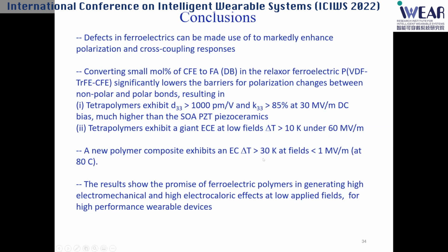We also showed that even new polymer composites, at very low electric field, can generate very large temperature swing. This result shows the promise of ferroelectric polymers in generating high electromechanical and high electrocaloric effect at low fields, which could lead to high performance wearable devices.